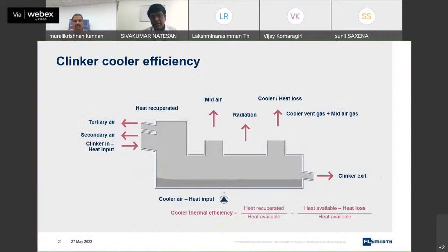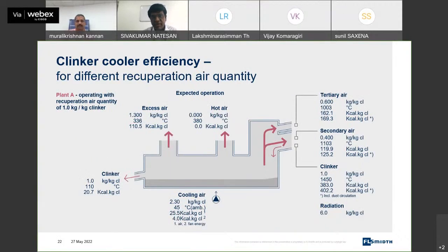And in general, as a parameter, when you try to evaluate a cooler, the correct evaluation is going to give us a benefit on how to optimize the cooler. Clinker cooler efficiency is a parameter which is calculated based on some theoretical formula, but based on practical measurements. And this is a balance which we have done for a particular plant, where you can see that the pyroprocessing system requirement is 1 kg of air per kg clinker back to the system. So when you put secondary and tertiary air added together, it is around 1 kg, and the cooler efficiency is calculated and heat losses is calculated.